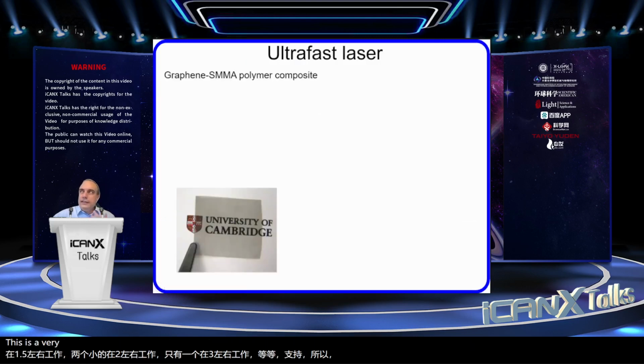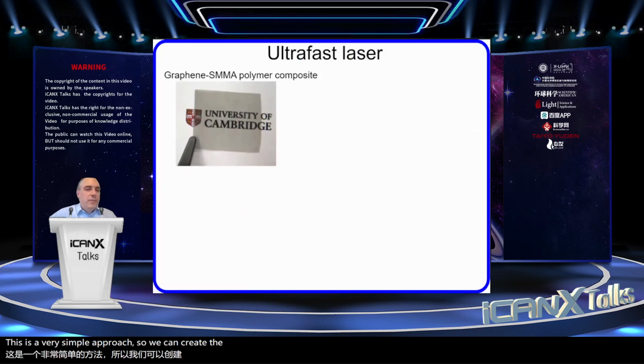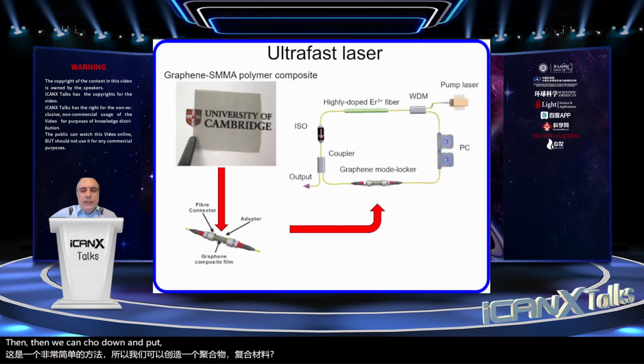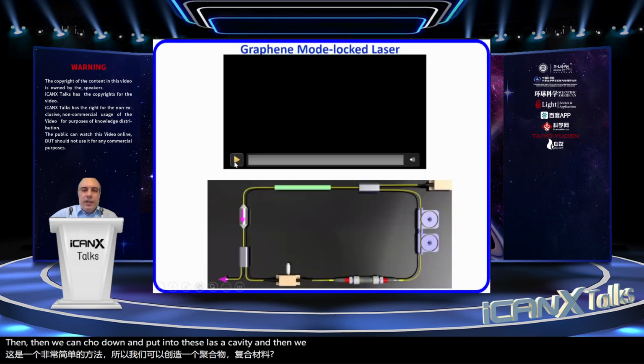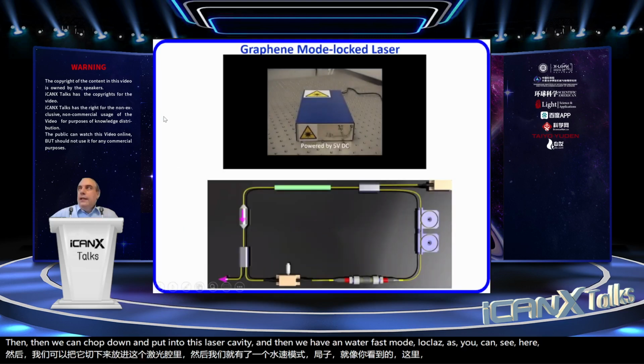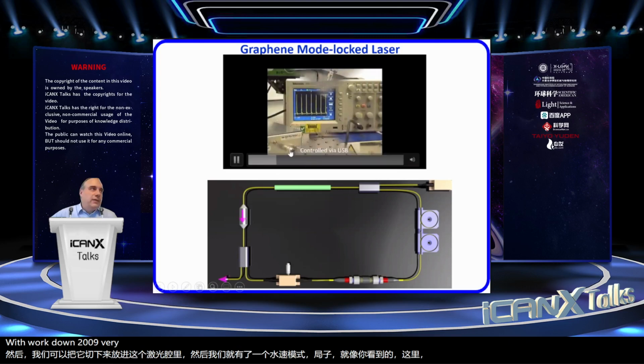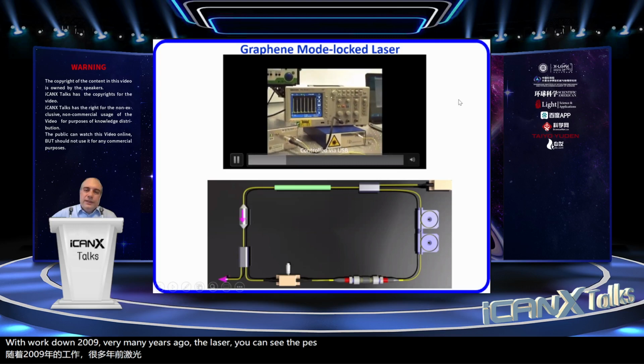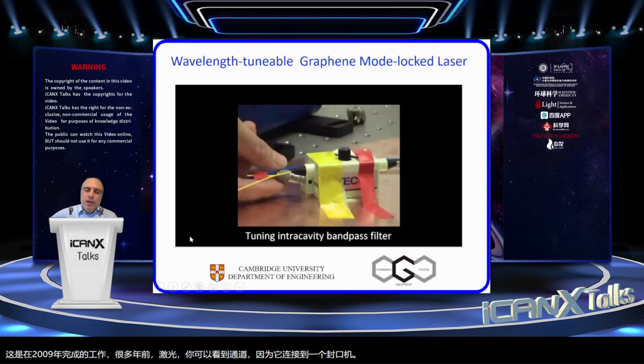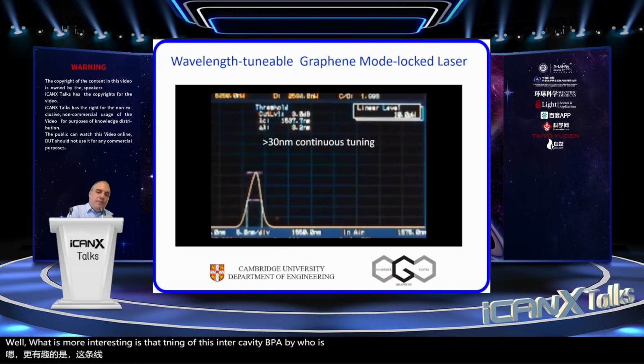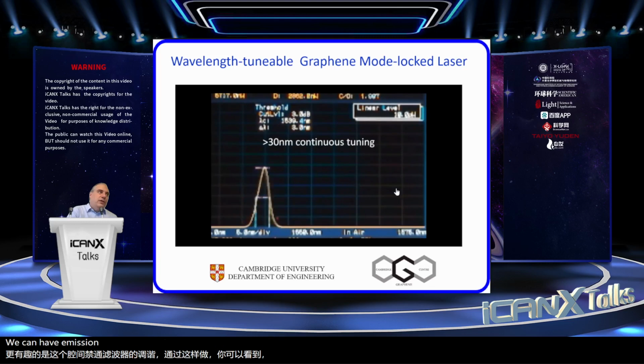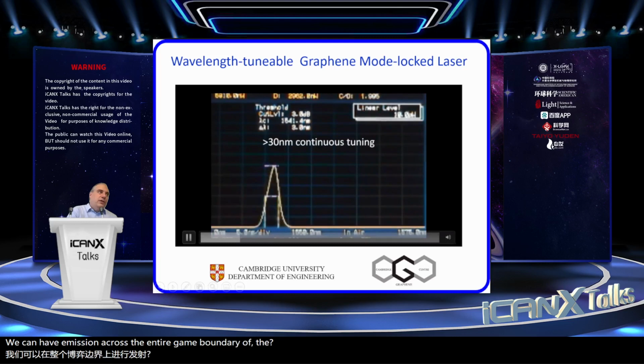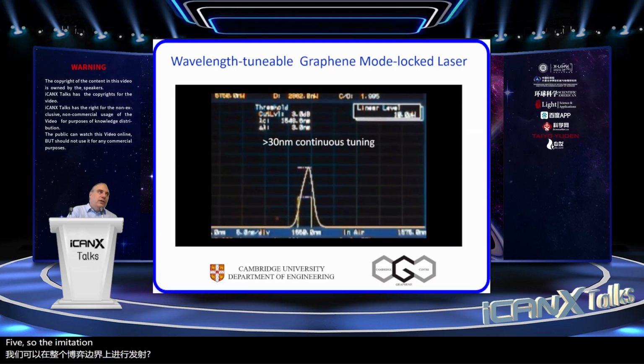So this is a very simple approach. We can create a polymer composite, then we can chop it down and put it into this laser cavity, and then we have an ultra-fast mode-locked laser. As you can see here, this is work done in 2009, already many years ago. The laser, you can see the pulses because this is connected to an oscilloscope. But what is more interesting is the tuning of this intra-cavity bandpass filter, and by doing so, you can see we can have emission across the entire gain bandwidth of the erbium doped fiber. So the limitation is not the graphene, the limitation is the bandwidth of the fiber.